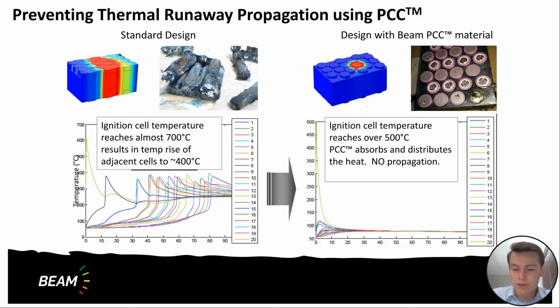So now moving into the benefits of PCC in solving this issue. I think this is just an introductory slide just to showcase how propagation looks from a data perspective. So we ran both simulations and experiments, top and bottom, for a battery pack that was a 10S4P, with about 1.5 millimeter spacing, so quite tight spacing. These were MG1 cells, so older model cells, I think about 2.9 amp hours, but high energy at the time.